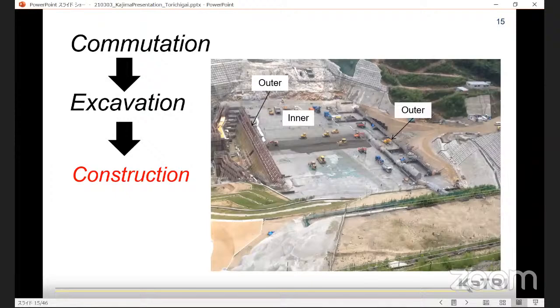As for the concrete of the dam, the composition of the concrete is changed depending on the outer part, where the surface is exposed, and the inner part, which is inside of the dam. For the outer part, highly durable concrete is used. On the other hand, for the inner part, concrete is used to reduce heat generation by reducing the amount of cement as much as possible, and by using a large size of gravel. The maximum size of the gravel is about 80 millimeters or 150 millimeters.